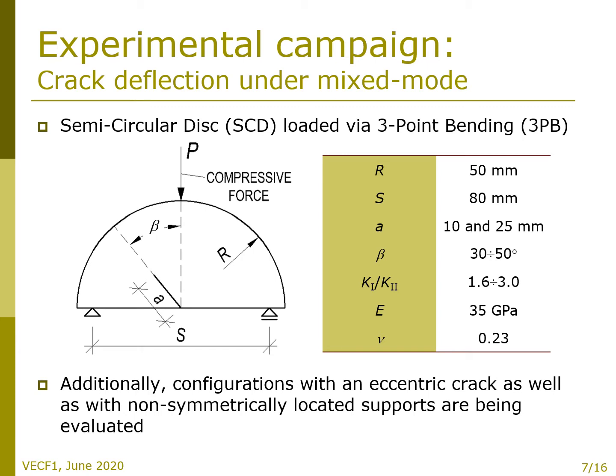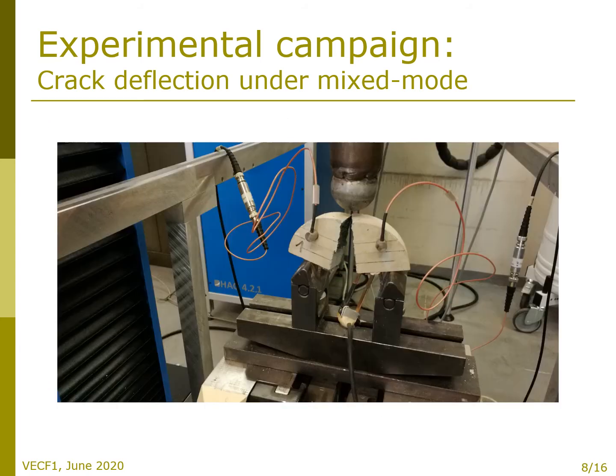We follow with further tests, and it is 3-point bending test on a semicircular disc with an inclined crack. In the table, you can see the dimensions and other parameters of the specimen during testing. The values are valid for the results presented within this video. Nevertheless, the campaign is more extensive. Also, configurations with an eccentric crack and with not symmetrically located supports are being tested, and results evaluated in order to get a complex set of data for final conclusions.